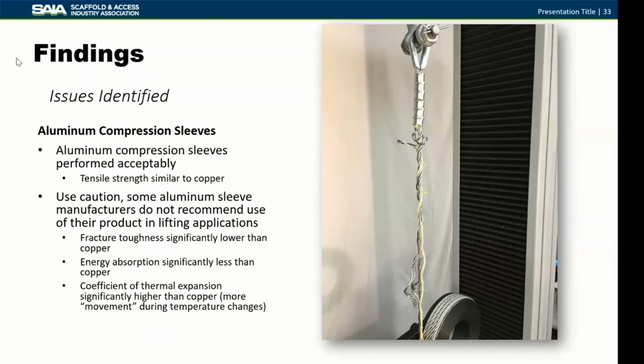In addition, the coefficient of thermal expansion of aluminum is significantly higher than copper, which would allow more of what we'll refer to as movement of the aluminum compression sleeves relative to the steel wire rope, significantly more movement during temperature changes than what you would experience with copper. So although the tensile strengths are similar and therefore the performance as a termination is similar, the long-term performance of aluminum gets called into question because of the fracture toughness and its ability to absorb energy.